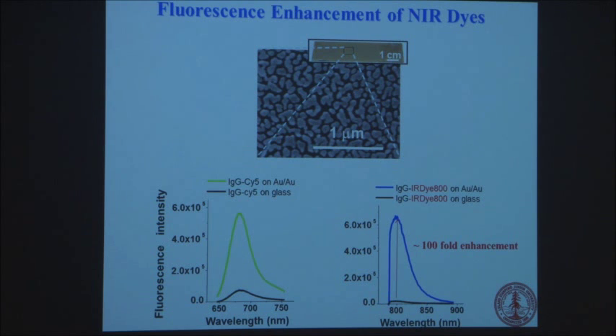So what's good about them, as I mentioned, is that if you put a fluorophore on the slide, the fluorescence can be enhanced. Now, a lot of you, if you work with fluorescence, know that metals would typically quench fluorescence. So this is why people rarely use a metal film for protein arrays or peptide arrays, because you don't get any fluorescence out, so you lose any detection sensitivity. But in these films, we found you can actually enhance the fluorescence of this IR dye I mentioned earlier for imaging by up to 100 times. So it's a very large enhancement of fluorescence.